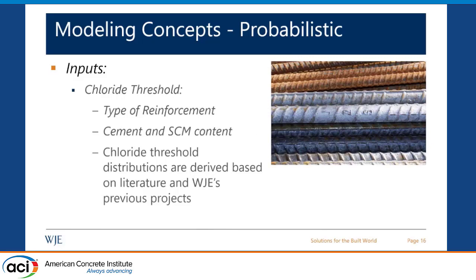For the chloride threshold, this is dependent on the type of reinforcement you're using, if it is black bar, galvanized, epoxy coated, stainless steel. And it's also a function of the cement content and supplementary cementitious material you have in your mix. So typically for our model, we define the chloride threshold based on data presented in literature, but we also keep refining that based on data that we have collected from previous projects. So we collect concrete cores and we look at the chloride concentration at the bar depth and the condition of the bar, and we build a database of this information that we can refer to define some of the distributions for corrosion resistant reinforcement.